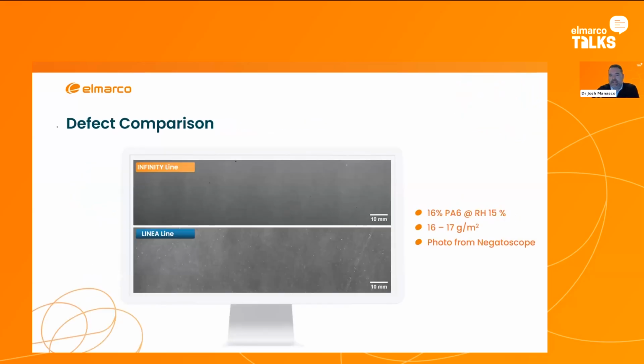bonus. And this is just one example on the light table looking at two materials that were produced from the same solution, 16% PA6, at a low relative humidity, which tends to cause a lot of defects in our Linea technology. So we wanted to test a kind of extreme condition where we know we generate a lot of defects, and you can see that there's quite a few less defects that are produced running the same conditions with the same, let's say, very difficult settings on the line.